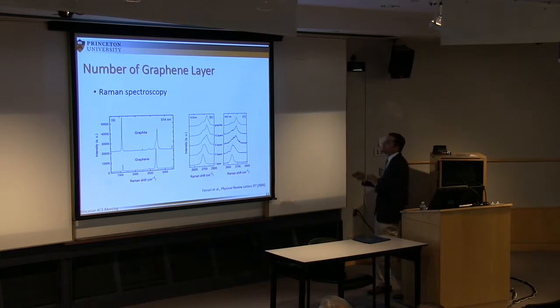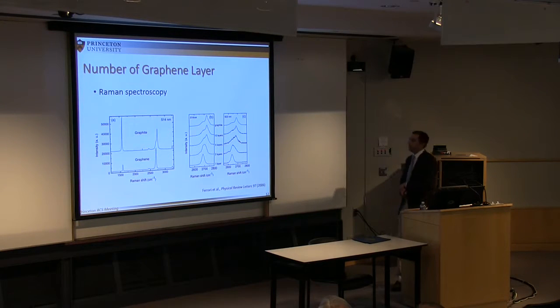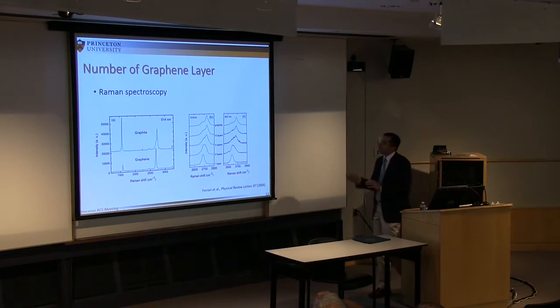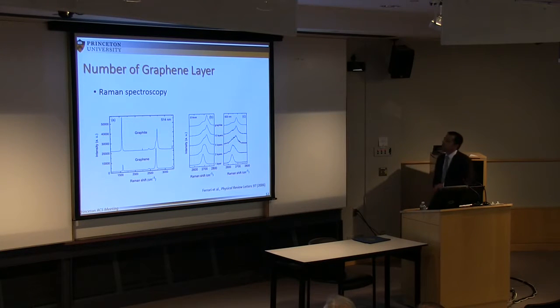Now, if we focus in particular on the 2D band, you see that when we have a single layer, independently of the excitation, whether you use the green or the red wavelength, you have the same conclusion. So it's not an artifact of the excitation source. In the case of a monolayer, you have a nice sharp peak. As soon as you have two layers, you have a broader peak with a shoulder. Why? This is simply due to the electronic structure of graphene. And as you go up further, up to 5 layers, for instance, you also have a shift. And clearly, this peak and the shoulder do not change anymore as soon as you exceed a few layers.